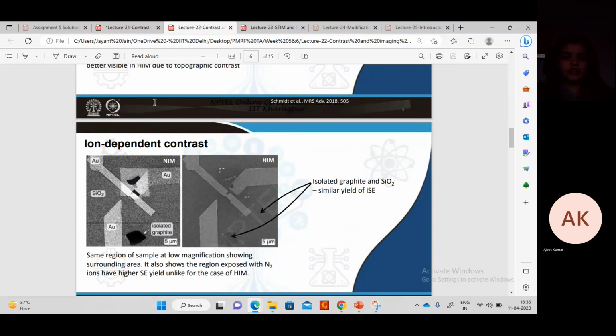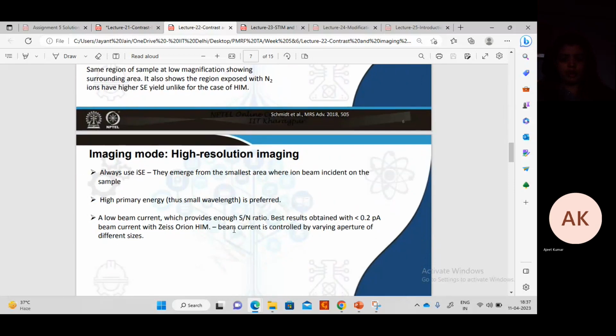And as I was telling, beam damage will happen in the case of a nitrogen ion microscope compared to helium, because even though the interaction volume and penetration depth are smaller with nitrogen, it will destroy the sample because it has higher energy compared to helium. So you cannot compare nitrogen ion to helium ion. If you use nitrogen, you will get better contrast, but sample damage will be very high compared to helium. But when you use helium, the contrast is not very good. So when you want to go for a BSE image, always go for electron mode, electron beam.